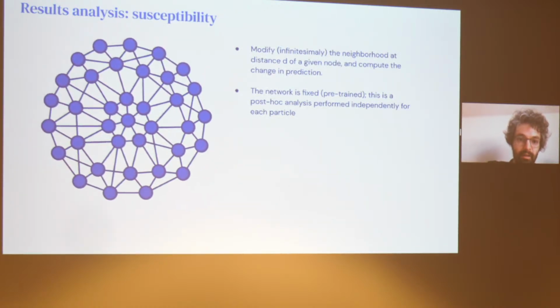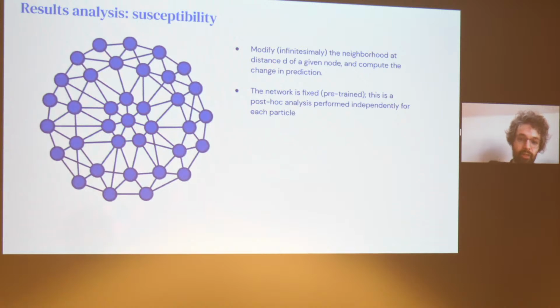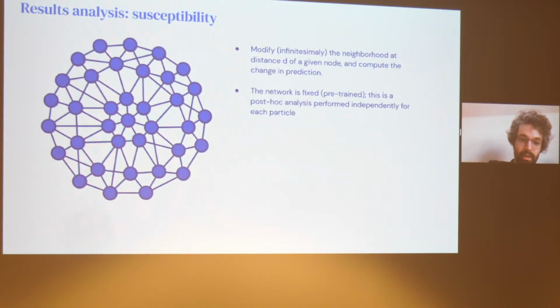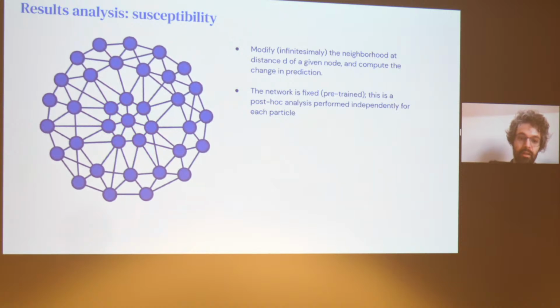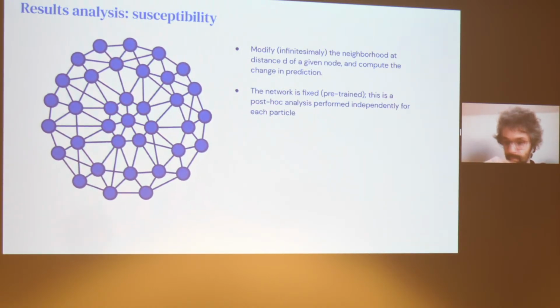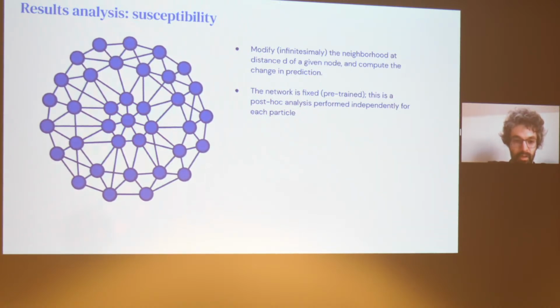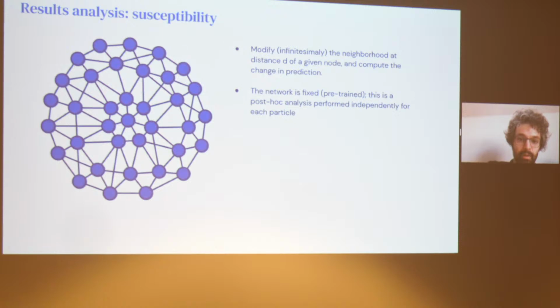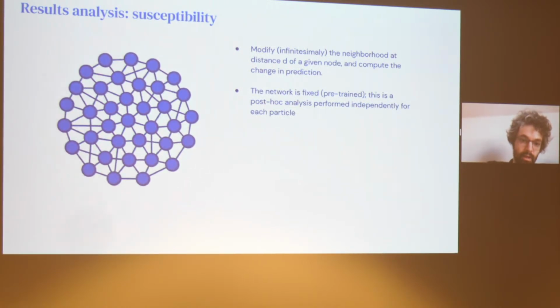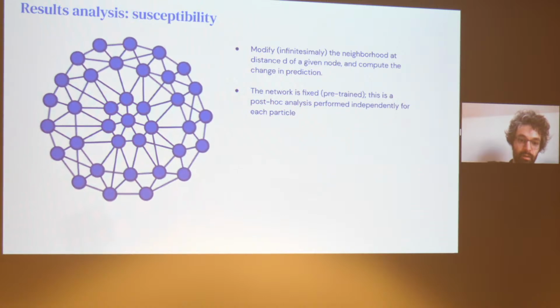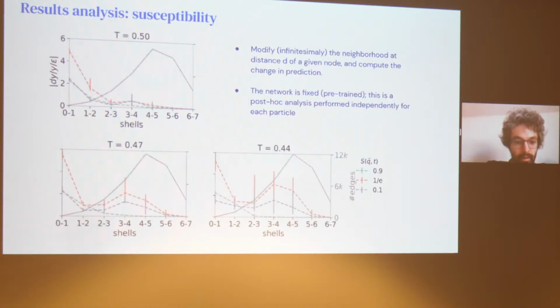The other thing we did is a slightly more gentle version of the previous one, where you don't remove nodes completely, but you just change the distance a bit. You take the shell at a given distance, and then you push all the edges, the distance on the edges, by some factor. So you're pretending that everything is a bit further away at a given distance. And again, you look at how much it changes the predictions. This is an infinitesimal change now, so we can look at the derivative of the prediction with respect to this change in distance. What we saw is this interesting behavior where, if you look at the 2 plots at the bottom, which are the lowest temperatures, the effect is the most pronounced at a given distance.